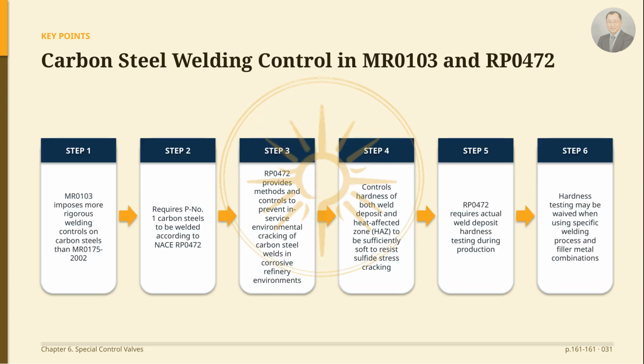Next, I would like to introduce the welding control requirements that MR0103 imposes on carbon steels. MR0103 requires more rigorous welding controls for carbon steels than those in the 2002 edition of MR0175. Specifically, it stipulates that P-No. 1 carbon steels must be welded according to another NACE document called RP0472. This RP0472 document contains methods and controls to prevent in-service environmental cracking of carbon steel weldments in corrosive petroleum refining environments. This regulation ensures that both the weld deposit and the heat-affected zone, or HAZ, are soft enough to resist sulfide stress cracking. Additionally, RP0472 requires actual hardness testing of weld deposits during production, although this hardness testing may be waived if certain welding process and filler material combinations are employed.